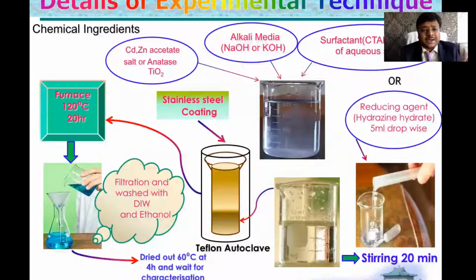I just started very simply with chemical ingredients, let's say cadmium, zinc acetate salt and anatase titanium dioxide, in an alkaline media. A clear transparent solution is there after stirring. Then we transferred it to another beaker and introduced some hydrazine hydrate as the reducing agent, which should accelerate our reaction rate and help the smooth growth of the nanomaterials we are looking for. After stirring for 20 minutes, you can transfer the fully transparent solution into a Teflon-lined autoclave. The high pressure will diminish the bulk property, and we will finally obtain the nanomaterials.